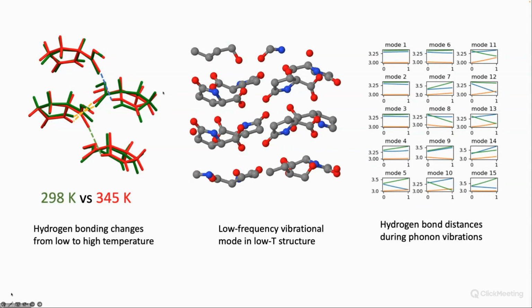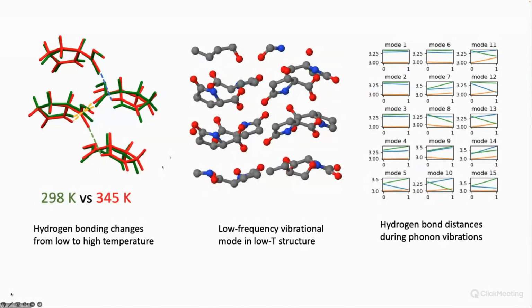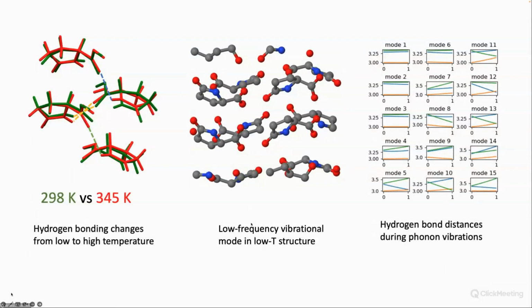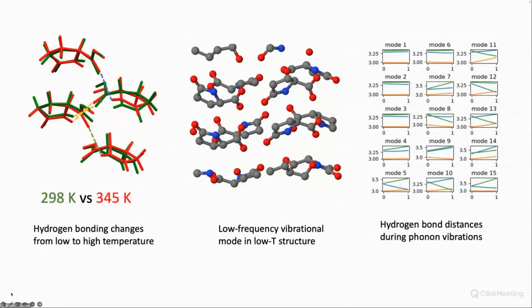So we were interested in looking at whether we could say something about which normal mode of vibration, which part of the lattice dynamics, is actually involved in the phase transition. Can we see some particular modes that could be the trigger of this phase transformation as we heat the system? There's one particular mode, this mode here, which has a frequency of about 40 reciprocal centimeters, that actually brings some of these hydrogen bonds in agreement between the two structures.